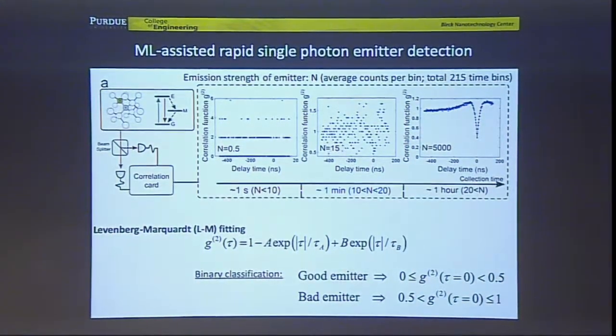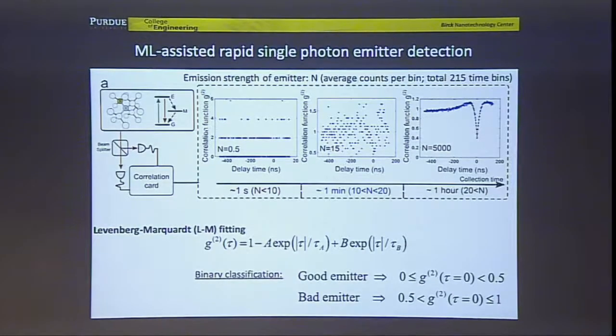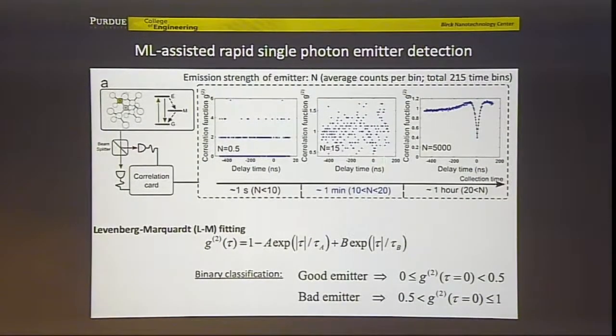So how do we do this single photon characterization? We do this anti-bunching experiment, same as the Hanbury Brown and Twiss experiment, well known. You use this correlation card and measure the signal as a function of delay between these two arms. Normally you obtain a function like this, the correlation, the co-detection event probability, as a function of delay, and it has this dip. Ideally, if it goes to 0, it is a single photon source. You always detect only one single photon, there or there. In reality, it never goes down to 0.